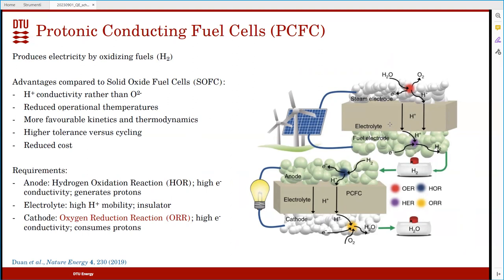So with a high electron conductivity and that is able to generate protons, the electrolyte with a high proton mobility and must be an insulator, and the cathode that can run the oxygen reduction, and has again a high proton electron conductivity and then consume protons. So those of you that are electrochemists or chemists in general know that the oxygen reduction reaction is a beast, and you have higher order potentials, and it's not the simplest reaction to run. So again, we came in and said we can try to solve it.